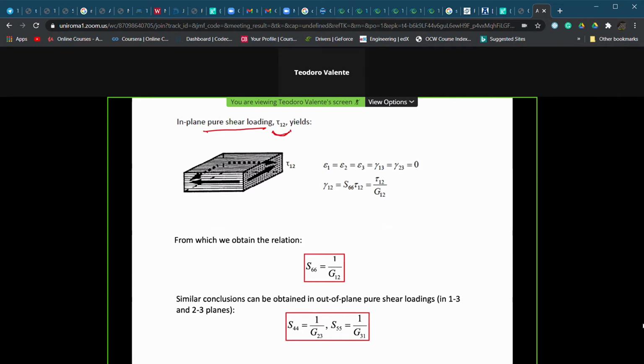So, for example, if you apply a pure shear loading in the plane 1, 2, we have just this shear deformation gamma 12, and all the others are 0, because we are talking about orthotropic materials, with no shear coupling. This is Hooke's law written in the case of shear deformation. You see here the shear modulus. This allows us to obtain this relationship to calculate the value of S66. Similar conclusions can be obtained in out-of-plane pure shear loading, that is the 1-3 and 2-3 planes, with the definition of the terms of the matrix, which are S44 and S55.